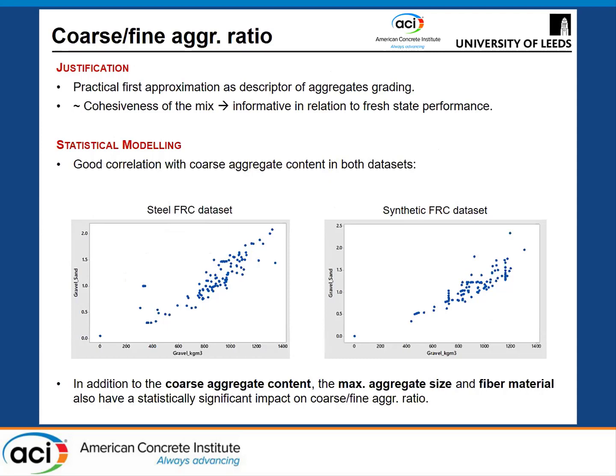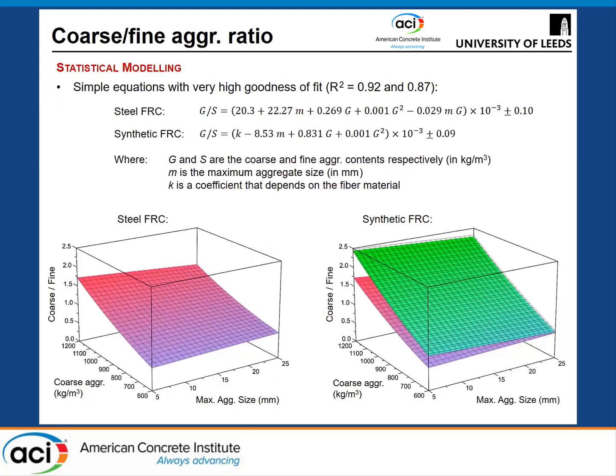If one plots the coarse to fine aggregate ratio in the database with respect to the coarse aggregate contents, you can see that there was a very clear correlation, suspiciously clear correlation, basically looking at the scatter plots. And it's also affected by the maximum aggregate size and the fiber material in the mix. So the regression analysis yielded these two very simple equations, which are actually very accurate, which are able to predict the coarse to fine aggregate ratio as a function of the maximum aggregate size, the coarse aggregate content, and also the type of fiber, obviously, because the equation is slightly different.